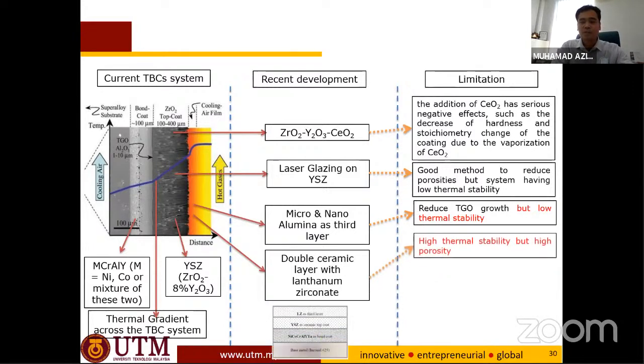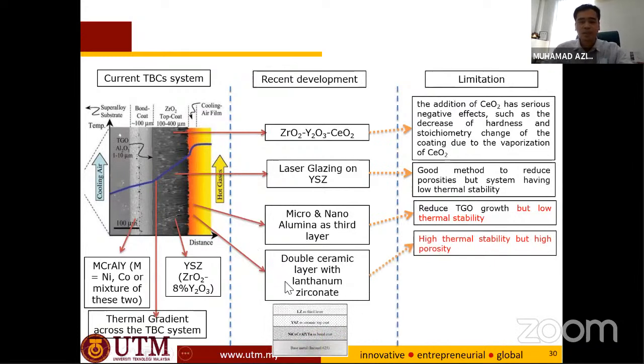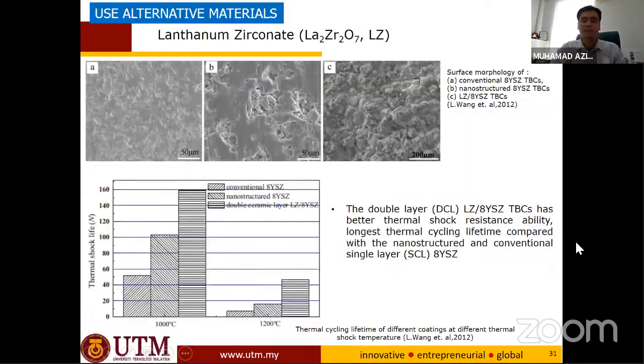Right, so then we create another layer, which is a double ceramic layer. You can see from this figure here, we have YSZ and we have LZ, with high thermal stability, because LZ has higher temperature stability compared to YSZ. But the problem is high porosity, so we need to cater for the problem of porosity. This is an example where we deposit lanthanum zirconate, LZ. You can see here there is a lot of porous structure.